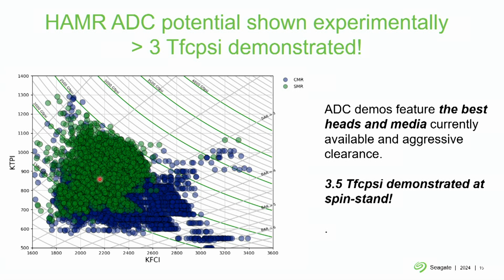And the green points are SMR, the blue are CMR, shingled versus conventional recording. I'll explain what that is shortly. So where we are right now is up here. These are lines of constant areal density, and this point is the 3.5 terabit per square inch areal density line. And we exceeded that with shingled magnetic recording. And what that means is that this is equivalent to a 6.2 terabyte per disk capacity.